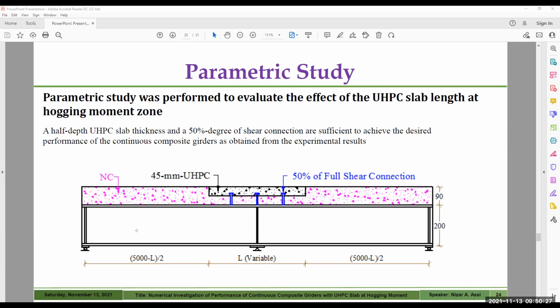From the experimental study, we concluded that half depth UHPC slab thickness and 50% degree of shear connection are sufficient to achieve the desired performance of the continuous composite girders. Therefore, I will continue with the numerical analysis using 50% of full shear connection and 45mm thickness UHPC slab. The only variable I will show now is the length of the UHPC slab, is this length.